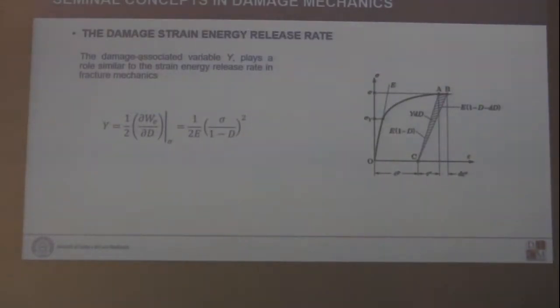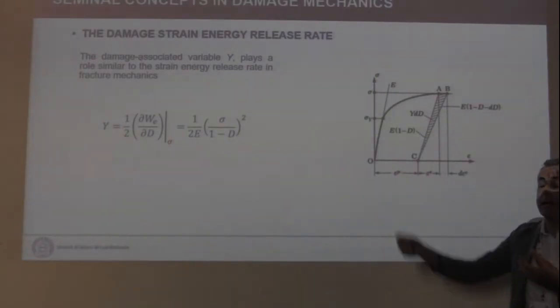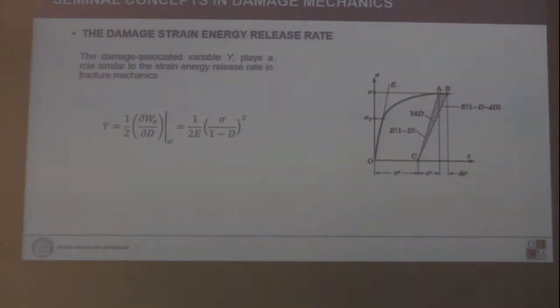The damage dissipation potential has to verify some principles. But at the very end, the important part is, and this is one of the beautiful seminal concepts derived in this framework, the fact that for each variable there is an associated variable. Stress is associated to strain. Damage is associated to the variable Y. The variable Y has a physical meaning, because Y is the strain energy release rate, which is not the Griffith criterion, but is the strain energy release rate that is released when the damage state, which is distributed into a reference volume,